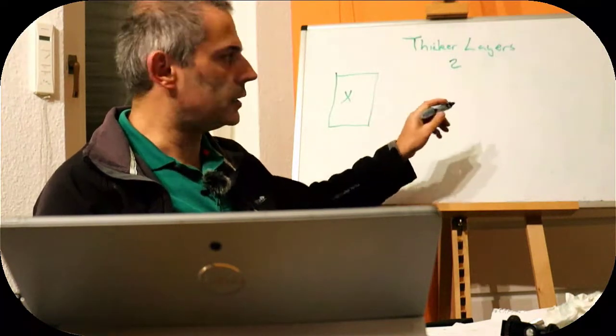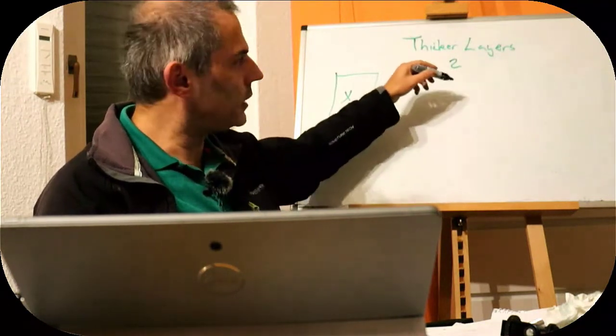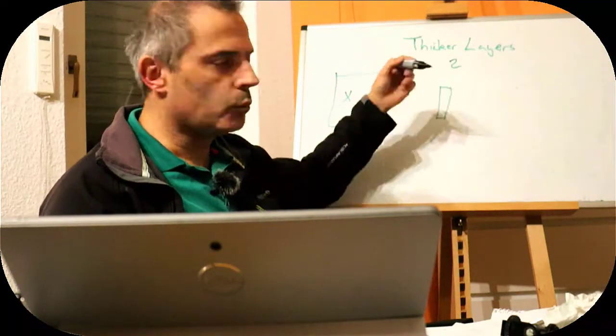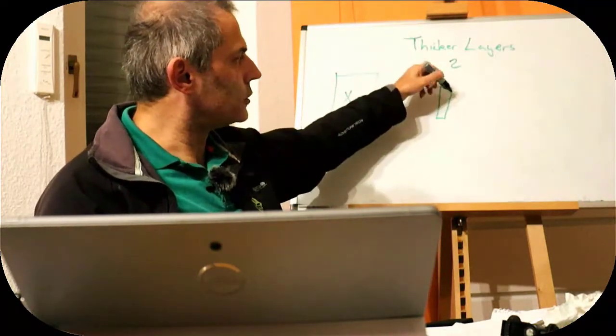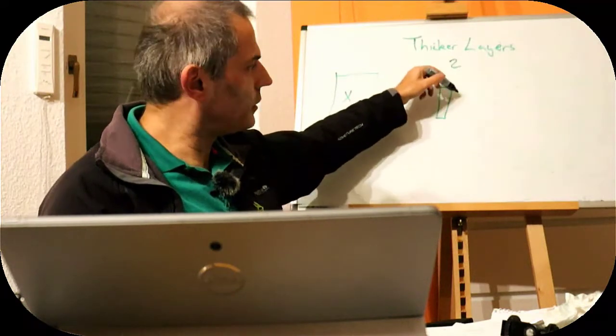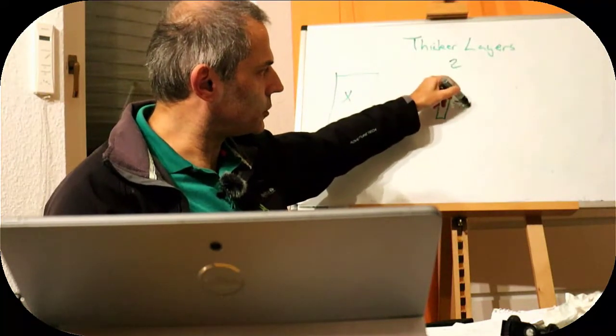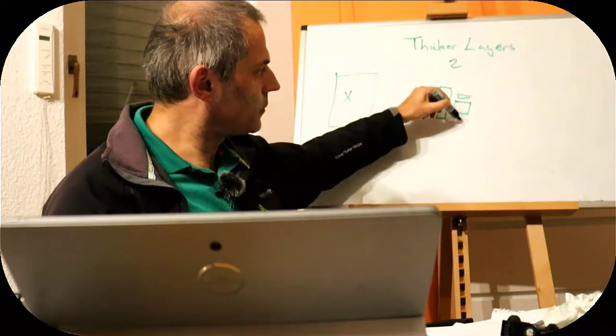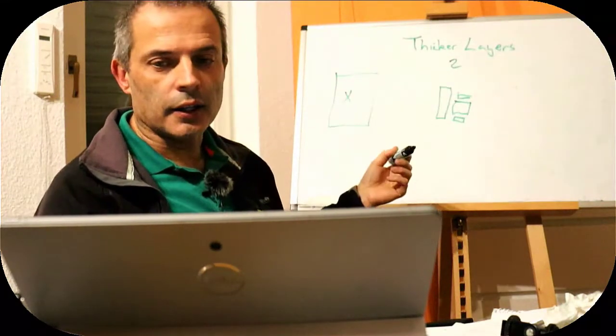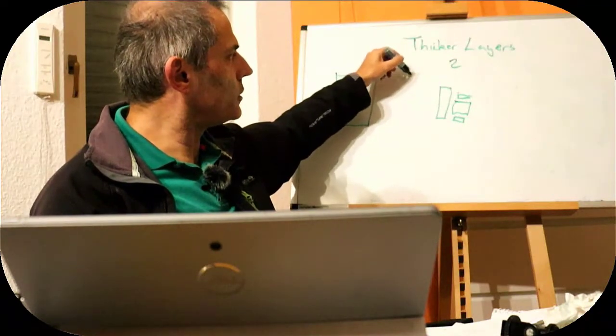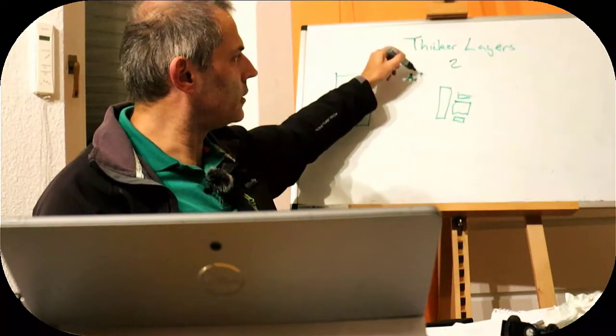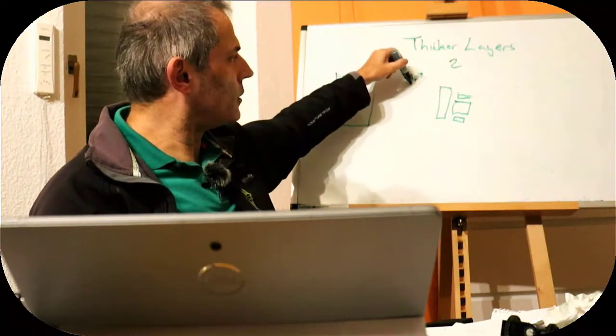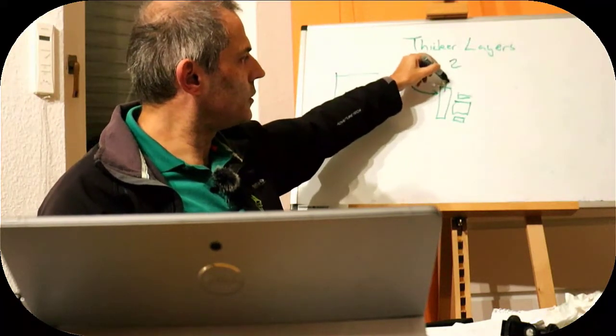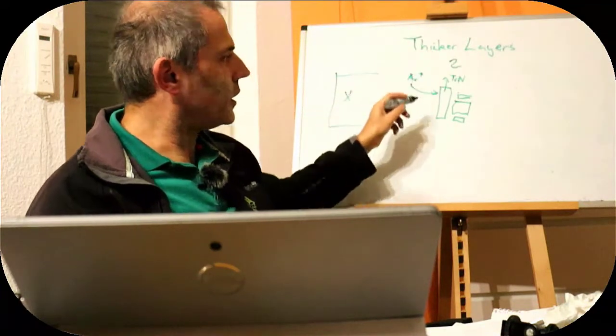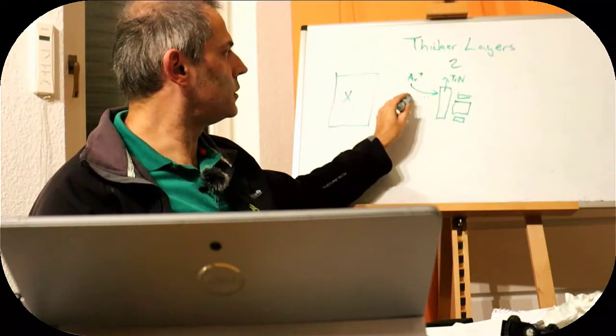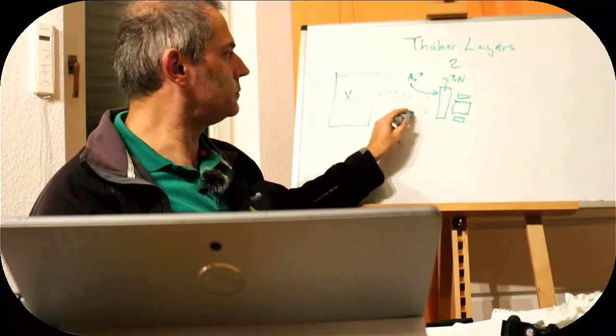So let's use titanium nitride. If we take a piece of titanium nitride, we could sputter it. So we can put our magnetron on here. That would be a magnet to direct the plasma, and that will generate some ions. Let's use argon ions because they are heavy and not very reactive, so we'll shoot them into our titanium nitride, and that will shoot off little clusters which will then go and hit our surface.